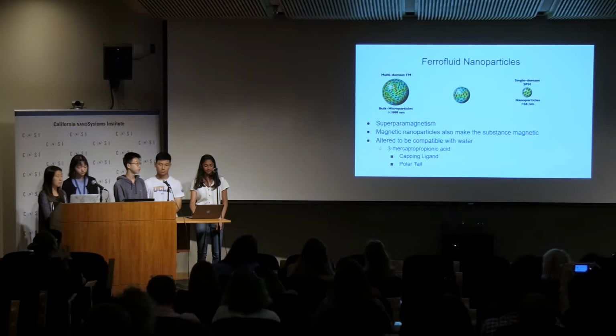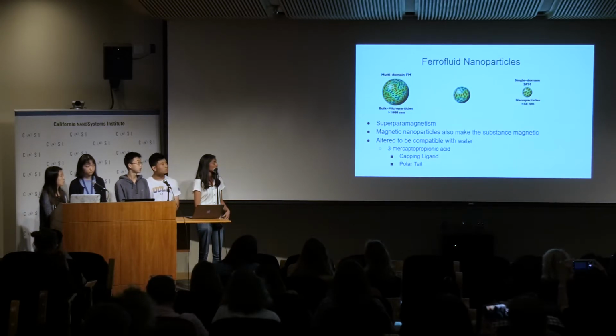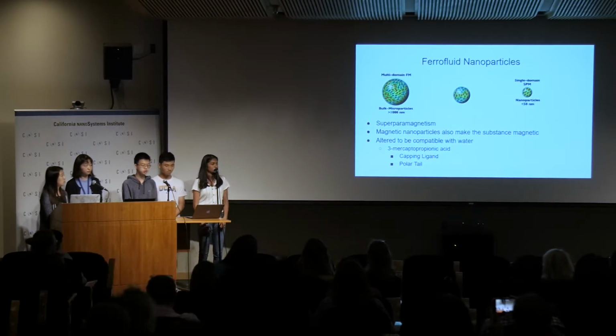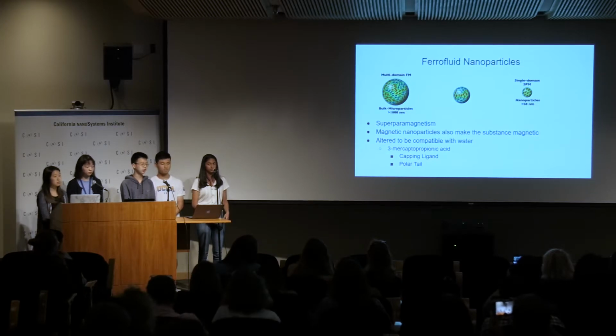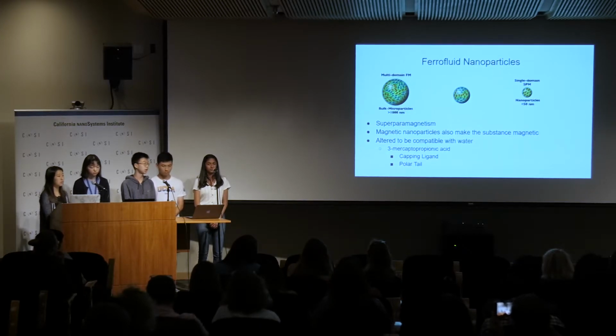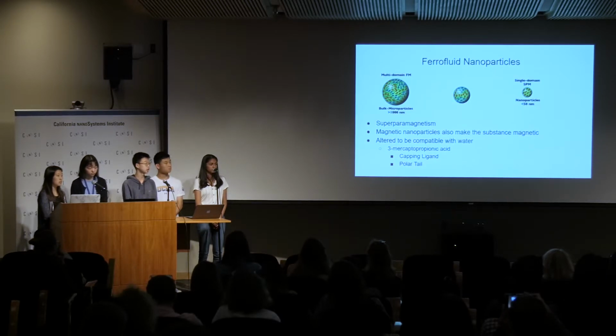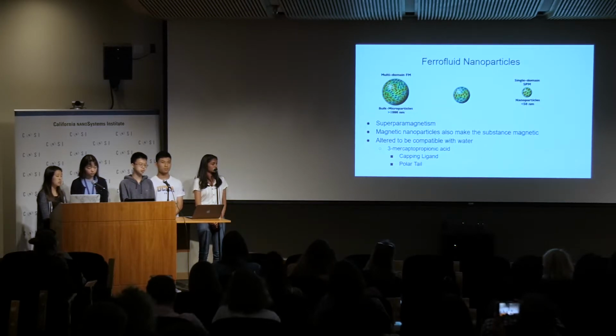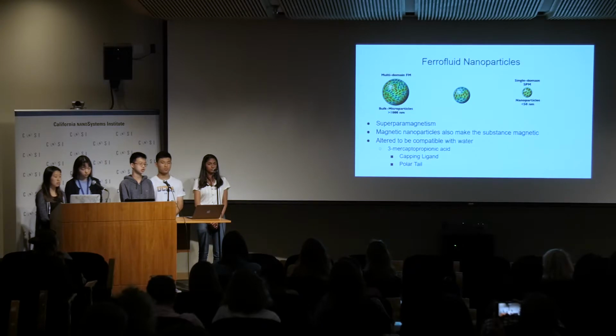To create our ferrofluid, we needed to create nanoparticles. Usually, microparticles have multiple domains. Domains are areas where the magnetic field of atoms align with each other. But as you go smaller into nanoparticles, eventually there's only one domain, which results in superparamagnetism. This makes them very responsive to a magnetic field.